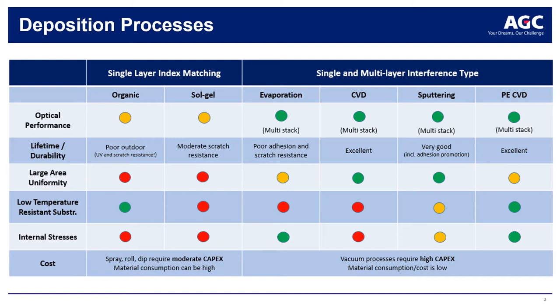Different fabrication methods and techniques have been used for the preparation of anti-reflective thin films. Organic coatings are applied on polymer substrates and can give excellent adhesion to the substrate without the need for a high-temperature curing cycle. The weakness of polymer coatings is that they frequently give rise to poor UV stability and scratch resistance, making them less suitable for outdoor applications.